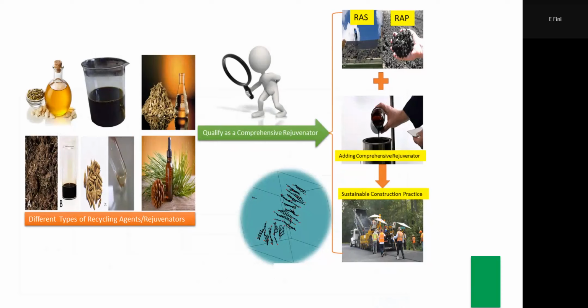I show you a bit of molecular modeling to say, if I have an aromatic structure, for instance, or a fused aromatic structure that does this type of activity within the aged asphalt, regardless of where the source is, as long as it has the same number of carbons and the same ring structure, it will do that action. If it's from bio, that's one advantage, which is renewable. Some of them are from waste, which is another advantage. But we have to separate the sustainability and bio-renewable side from the molecular efficacy of the action of rejuvenation.